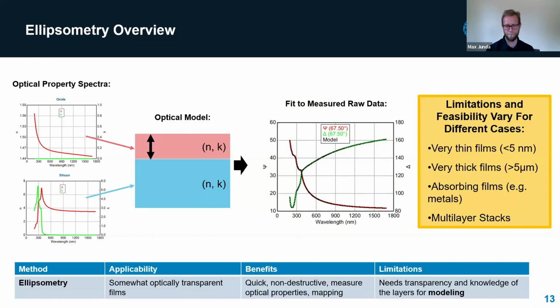First, the raw data. So that figure there, this is what the ellipsometer actually measures. And what we're showing here is the x-axis is wavelength, and we're showing two lines, and they're psi and delta. And without going into too much detail, what these are telling us is the ellipsometer light beam is polarized, and we reflect it off of the sample, and in reflecting off of the sample, the polarization state changes. These lines both tell us how the sample changed the polarization state. I will leave it there. And then that's what we get.